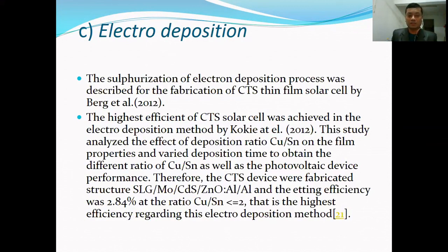with the structure: SLG substrate, then molybdenum, then CdS, then zinc oxide, and aluminum alloy. The efficiency was 2.84%. The copper to tin ratio was 2, less than or equal to 2. That is the highest efficiency regarding the electrodeposition method.